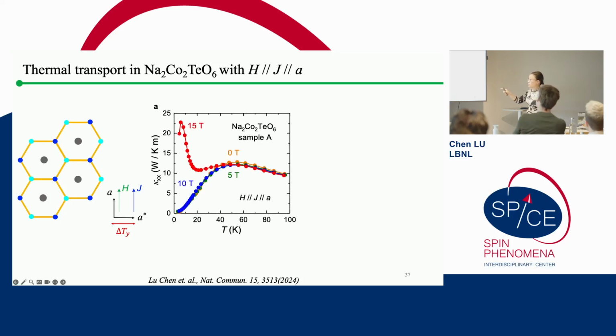The figure in the middle is the thermal conductivity versus temperature taken at 4 different fields. You can see here, the 0, 5, and 10 Tesla curves are almost on top of each other, but the 15 Tesla curve is extremely different. The real reason is that in this material, the thermal conductivity is mainly carried by phonons, and the phonons are mainly scattered by spin excitations. At 15 Tesla, you have already entered the so-called gapped phase, which means all the spin excitations are gapped out. So the scattering of phonons by spin excitations strongly decreases. That's why you have a strong enhancement of the thermal conductivity at high field and only at low temperature.